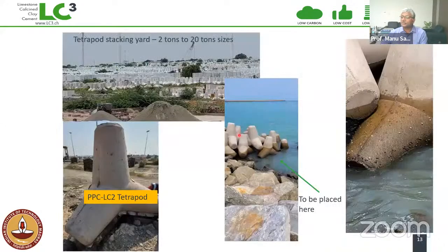And you can see the number of tetrapods that they have in this site. It's a stacking yard. The tetrapods come in different sizes, 2 tons to 20 tons, very large variation. And the tetrapod is expected to be placed in this location where it's going to be subjected to constant splashing of the seawater and chloride intrusion. So we will obviously monitor the stability of this material from time to time to ensure that we are getting the best performance out of these LC2 tetrapods. Here, again, very vast amounts of concrete are needed.